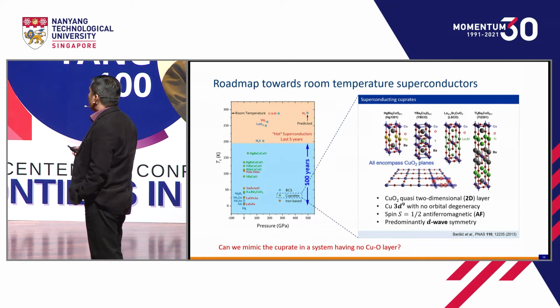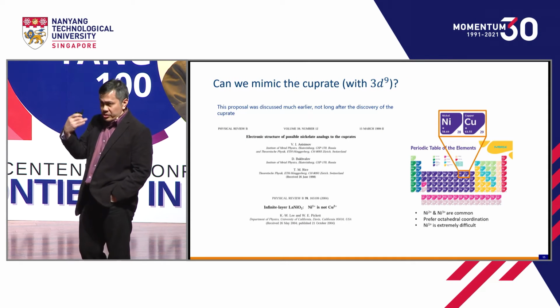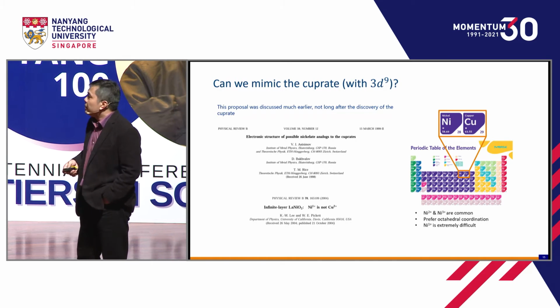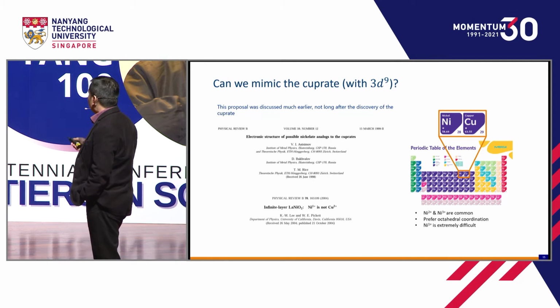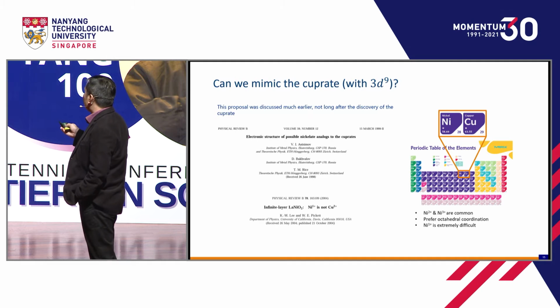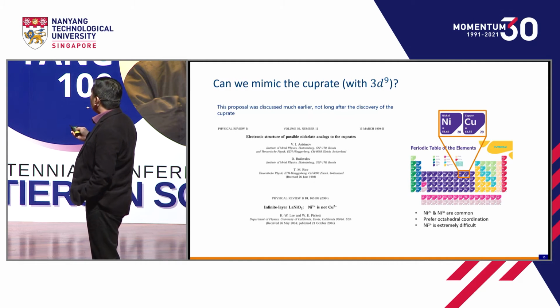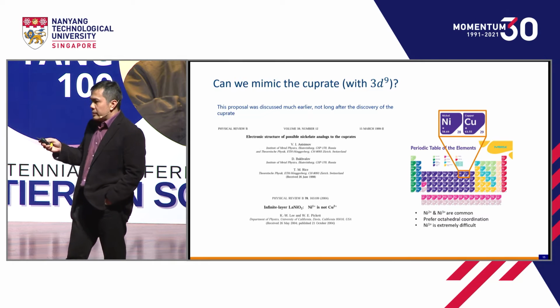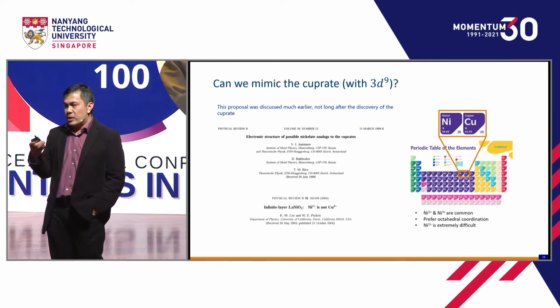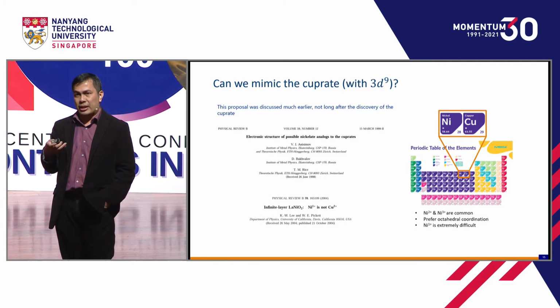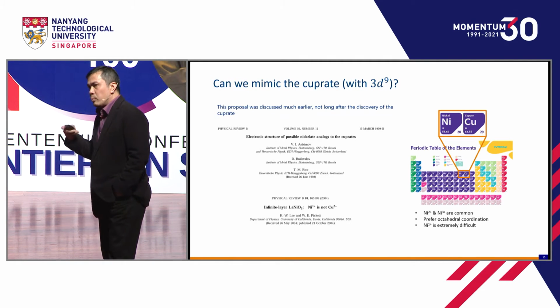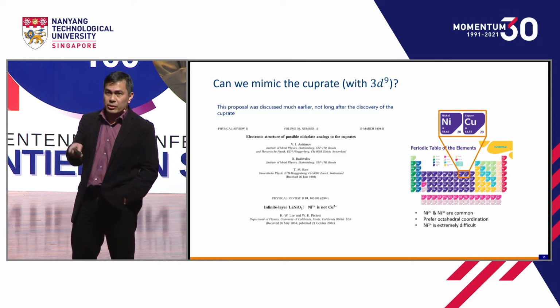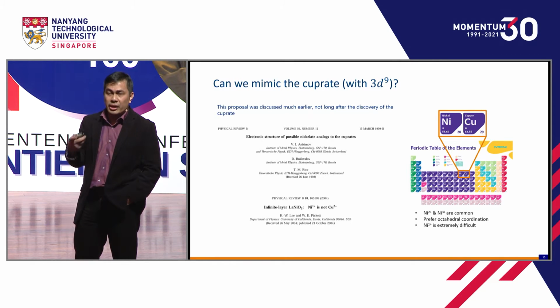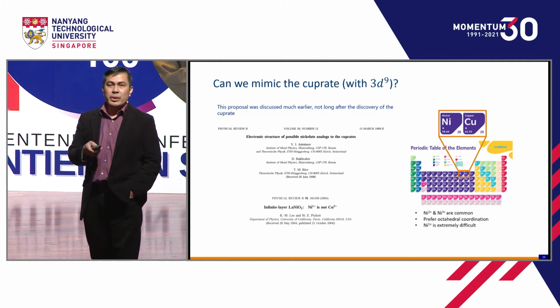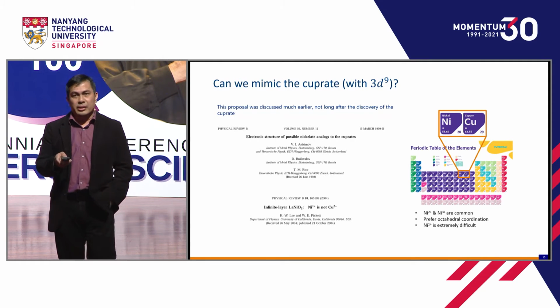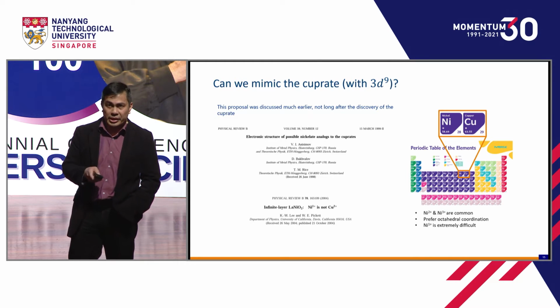So can we do that? Well, not long after the discovery of the cuprate itself, it was proposed in discussions that if you look just at the periodic table, next to copper there is nickel, and people proposed replacing copper with nickel. Again, the key point is this 3d9 electronic state, but nickel has stable 2+ or 3+ states, right? This only leads to 3d8 or 3d7, so you cannot achieve 3d9. The only way to achieve 3d9 is to make nickel 1+ valence. And this is very difficult and not stable in nature, okay?